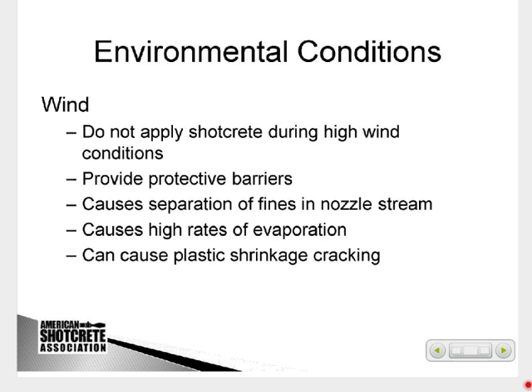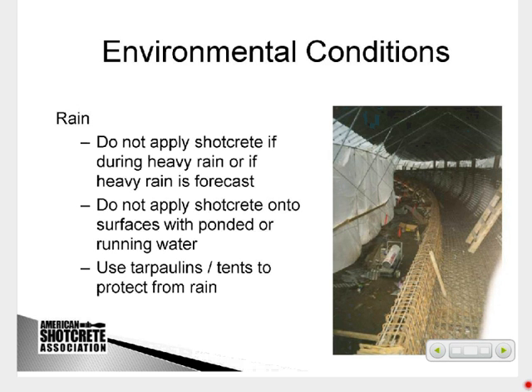And also because we have the surface exposed, if it's very windy, it does lend itself to early age plastic shrinkage cracking, where you may need to consider fogging again, or some kind of protection to keep the wind off the surface, which would not be that much different than if you're casting a large floor that's exposed to windy or dry conditions or hot conditions.